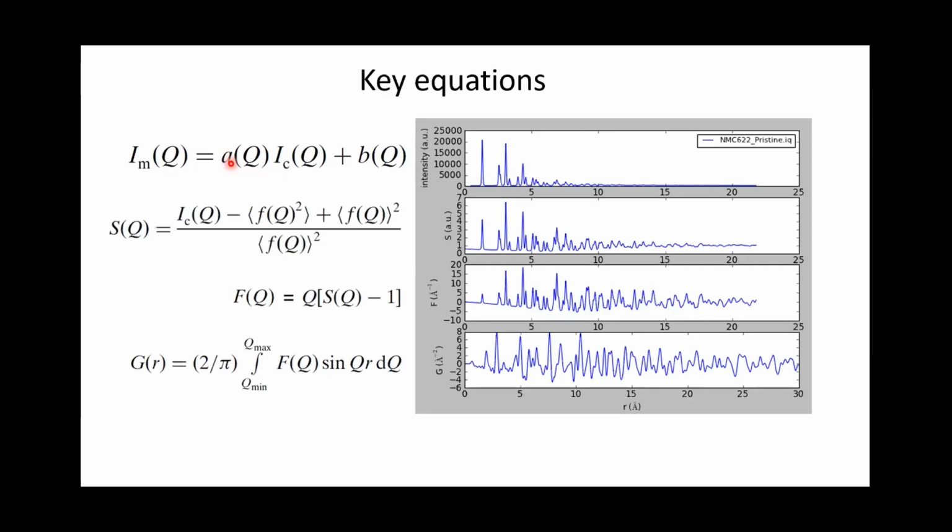If you remember last time's lecture, we did encounter a scenario in which we needed to input this number. The software asks us to input the polarization number, which is typically 0.99, very good for NSLS-II. But for a lab X-ray source, you probably get 0.5 or 0.6. So this polarization factor also comes into play and adjusts your intensity. Keep those things in mind.